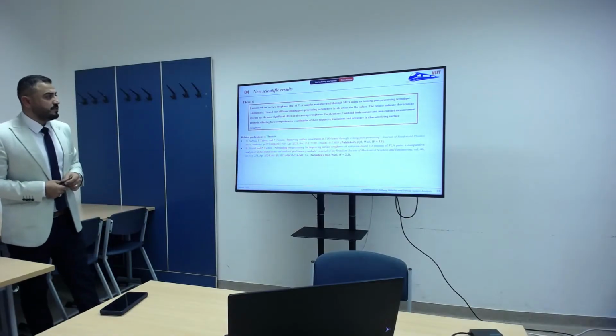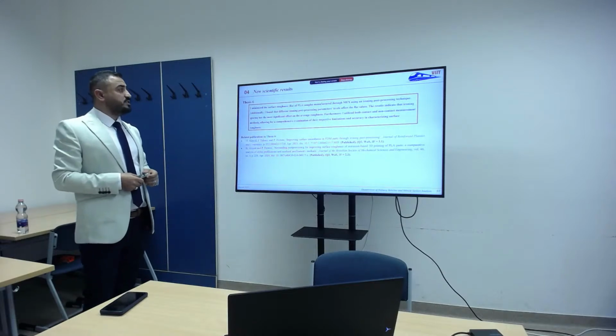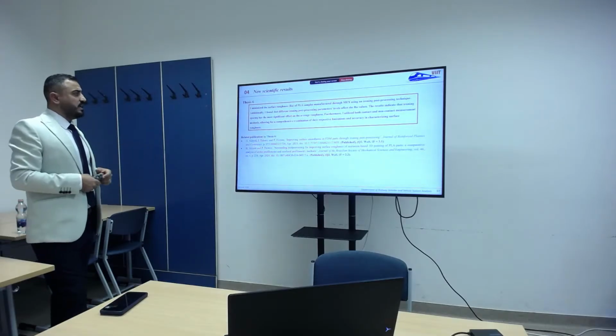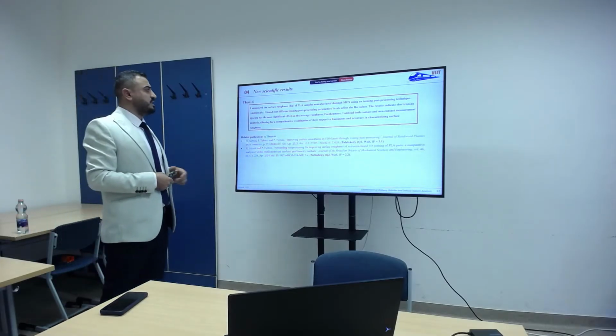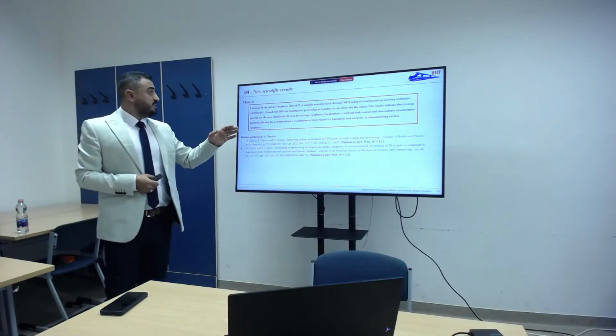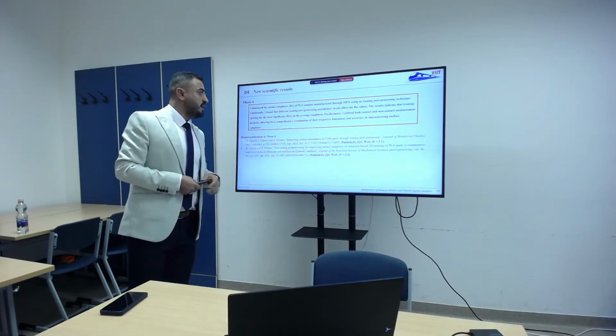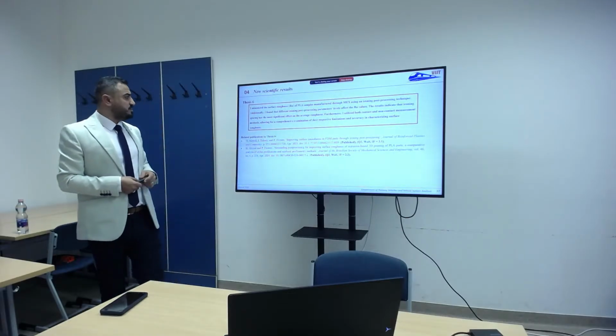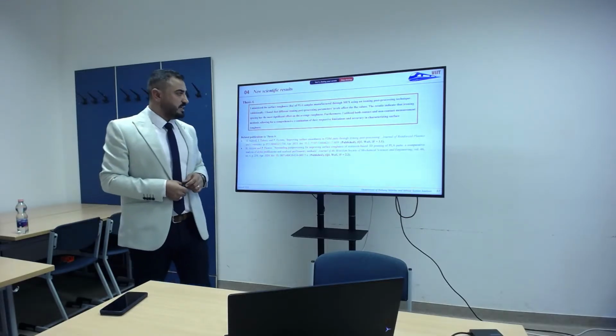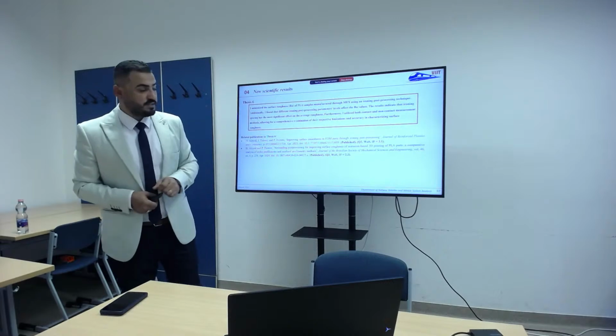So, thesis number 6 stated that I minimized the surface roughness of PLA samples manufactured by material extrusion using an ironing post-processing technique. Additionally, I found that different ironing post-processing parameter levels affect the Ra value. The results indicate that ironing spacing has the most significant effect on the average roughness. Furthermore, I utilized both contact and non-contact measurement methods, allowing a comprehensive examination of their respective limitations and accuracy in characterizing surface roughness. And this is the application related to my thesis point.